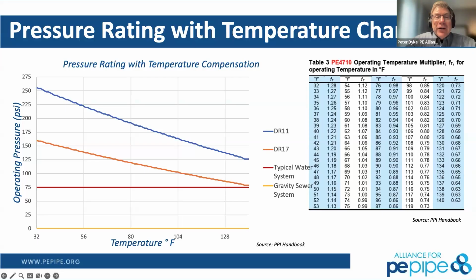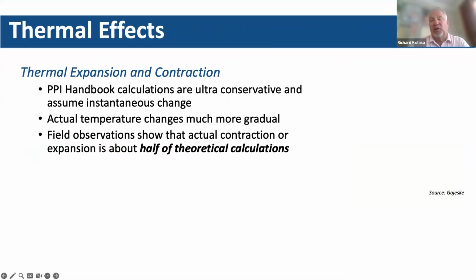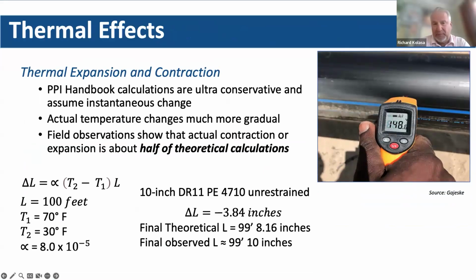Yeah, Peter. So Richard, last week when we did this data center, we had close to 600 people on the call, and we were talking about the three different pipe types. We were talking about polyethylene that's good to 140, PERT that's good to 180, and PPRCT that's good to mid 200s. And it's not often that we get to talk about the other pipe types, but that limit with each pipe type really becomes evident in that type of application. Oh, absolutely. And that's really vital because also not only it's the location of the polyethylene versus the other pipe types too, because PERTs and PPRTs are typically used inside. So you can transition from a polymer to a polymer.